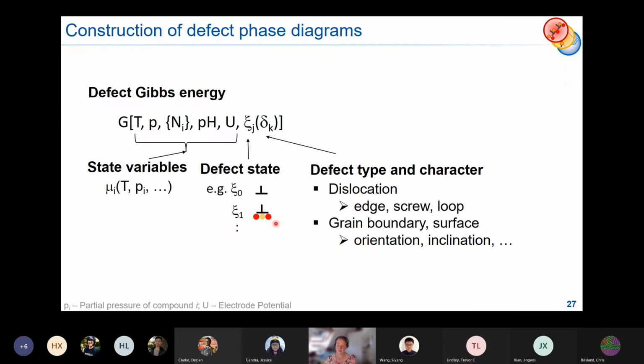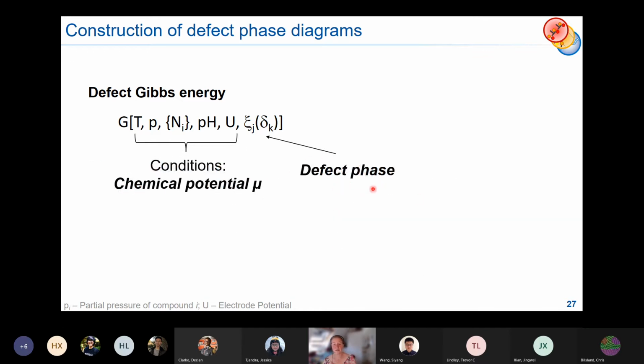So we can then, in theory, go and calculate Gibbs energies for the defects. We'll have state variables like the temperature, the pressure, the defect state. We actually need to think about all the different kinds of defects, for example, edge or screw dislocations, a boundary orientation, and so forth. And all of these describe the defect phase, and the conditions are essentially described by the chemical potential.